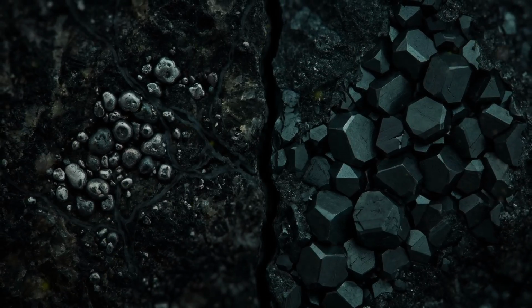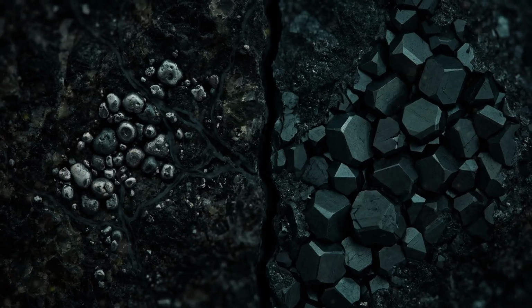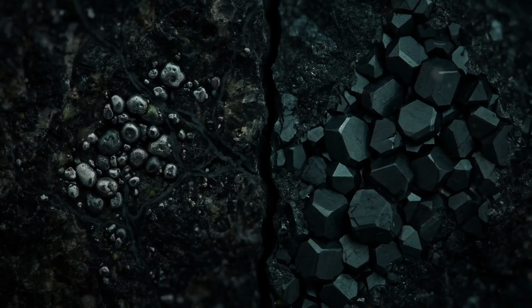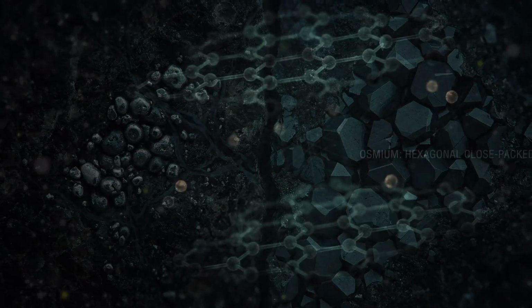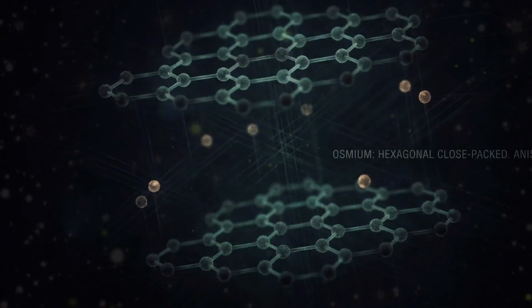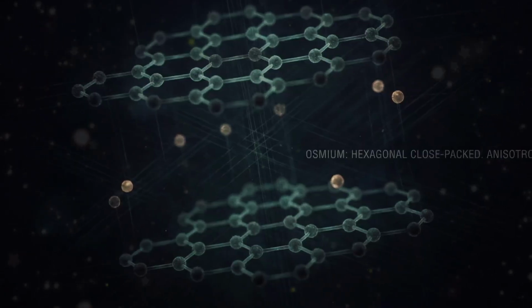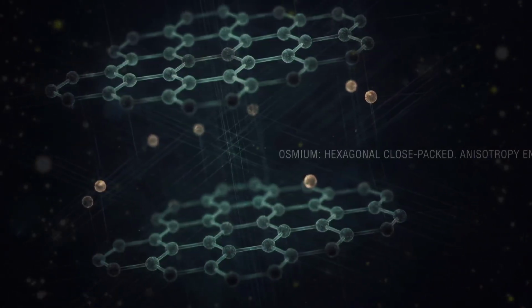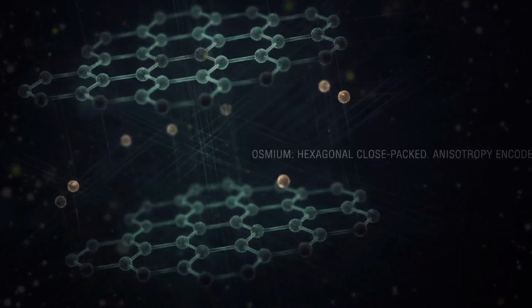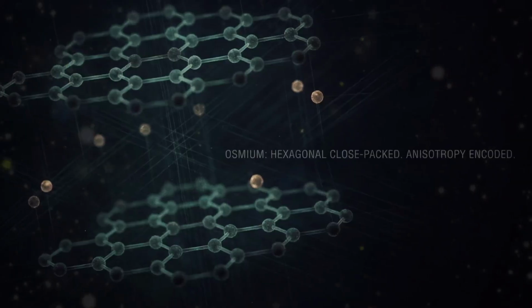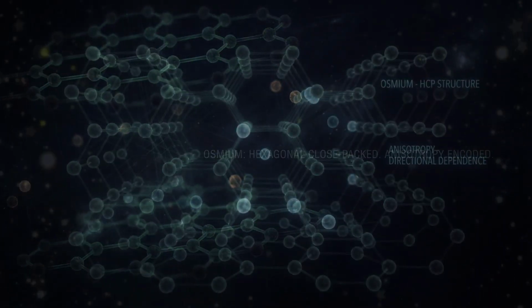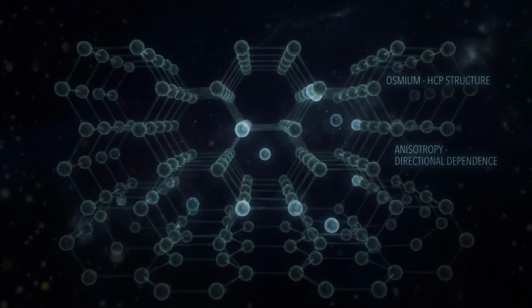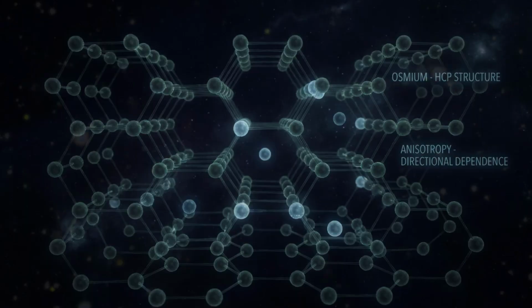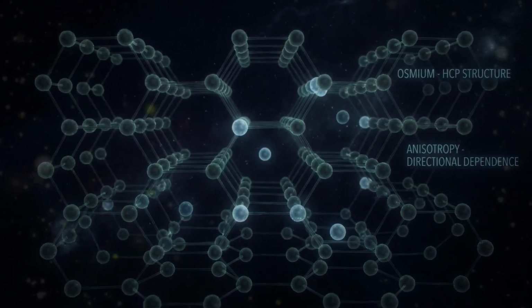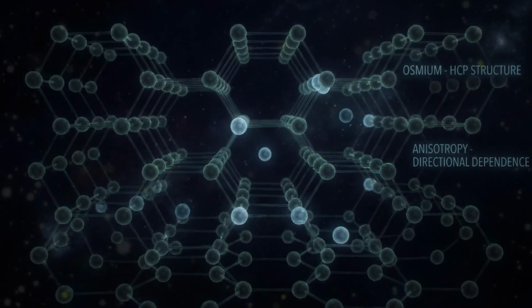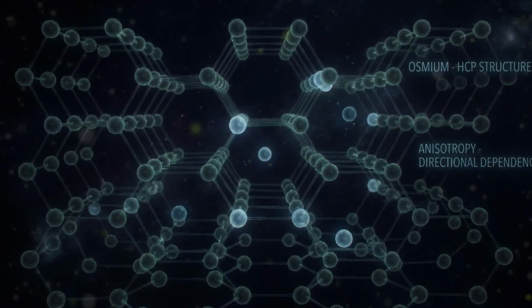Osmium, which competes with iridium for the distinction of being the densest naturally occurring element, is also among the hardest of all metals and carries the highest melting point of the platinum group elements, approximately 3033 degrees Celsius. Its crystal structure is hexagonal close-packed, distinct from the face-centered cubic structure of platinum and gold. And this structural anisotropy gives it directional differences in mechanical properties. In geological settings, osmium occurs not as pure metal, but predominantly as an alloy with iridium, known as osmiridium.